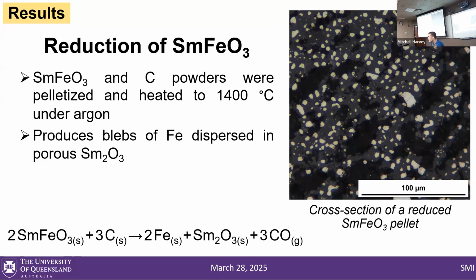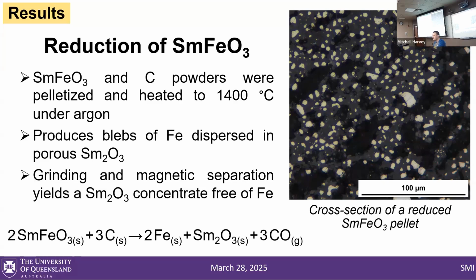But the resulting product is blebs of iron dispersed in a porous samarium oxide matrix. And unlike the oxidized magnets, the continuous phase here is brittle - it's the brittle samarium oxide. So it's very easy to grind.